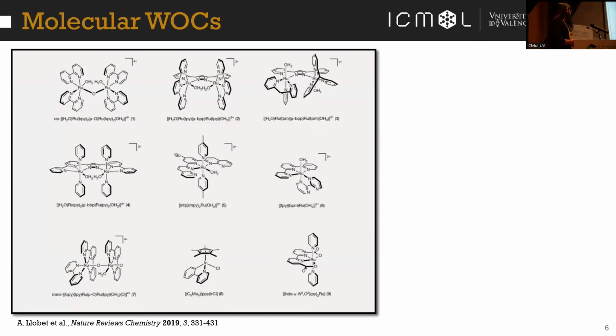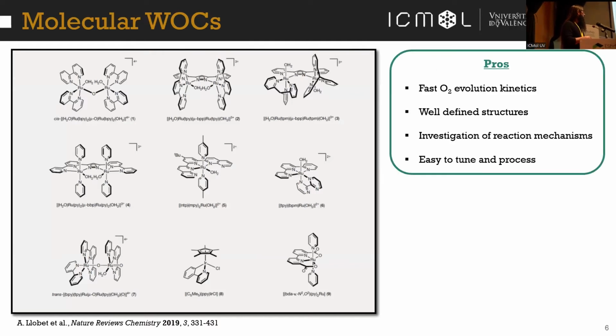Let me show you some molecular water oxidation catalysts. In these catalysts, we have a metal ion, which is stabilized by an organic ligand. They are pretty good, showing fast oxygen evolution kinetics. They are well-defined structures as they are molecules, so they are very easy to characterize, and they allow us to study the reaction mechanisms.